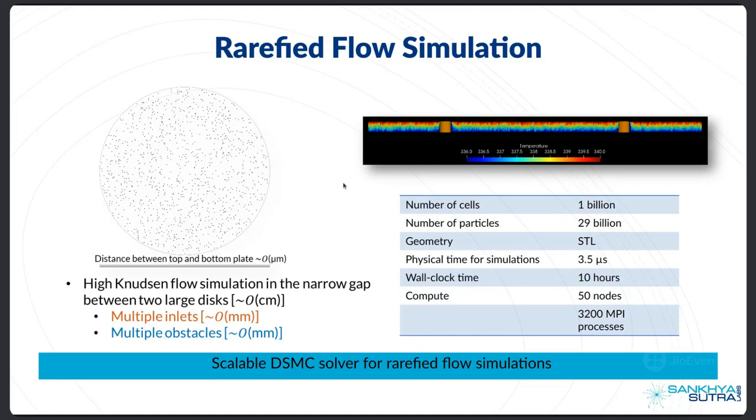the wafer, the heat transfer helium gas at a certain flow rate is flown just below the wafer. Because of the aspect ratio, the Knudsen number here turns out to be quite large. It is order one or higher than that. And for that, we have used, again, these direct simulation Monte Carlo methods to carry out simulations and understand the temperature and flow behavior in the narrow region just below the wafer, so that the process conditions just below the wafer can be optimized, and we have a uniform temperature on top of the wafer.